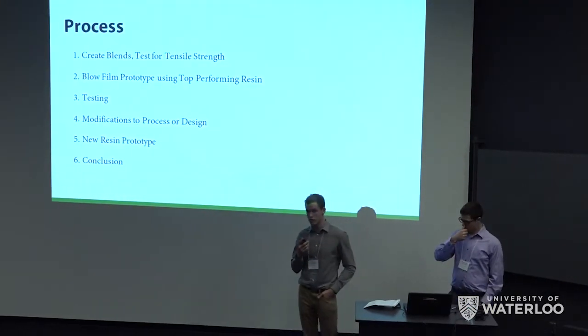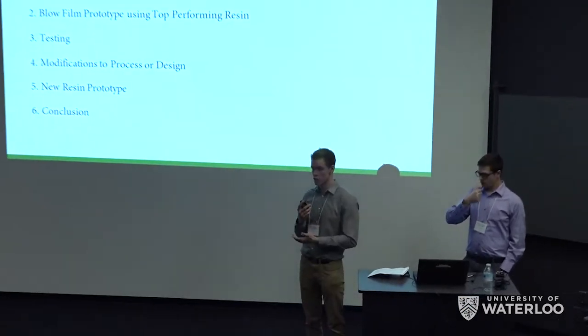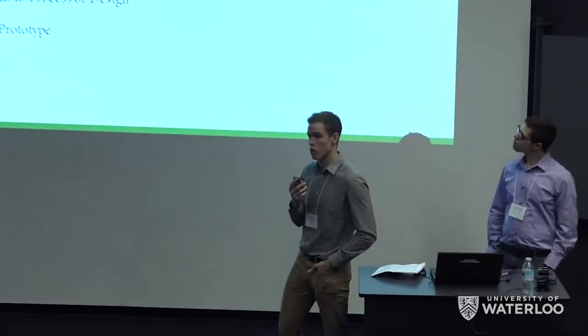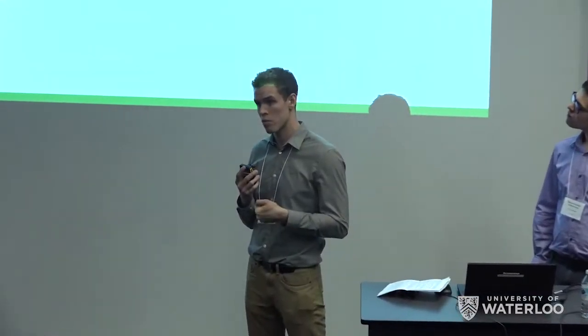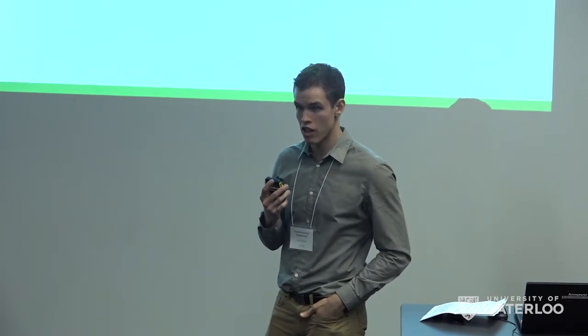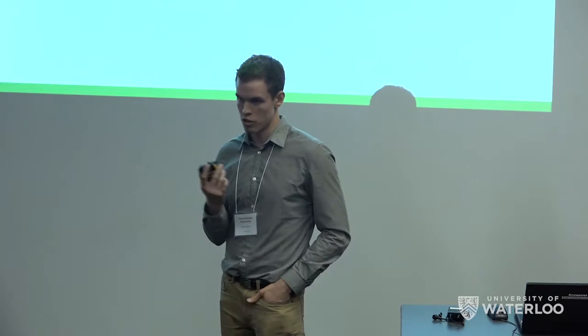So to actually bring these from an idea to a final prototype, what we did is first we blended these polymers, and then we tested the mechanical properties of injection molded bars. From this, we chose the best potential candidate to go to a manufacturing facility and blow these into a film. After that, we analyzed and tested the films and figured out how we could improve this for a second prototype, and then from there, analyzed those and concluded what further processes we could work on.